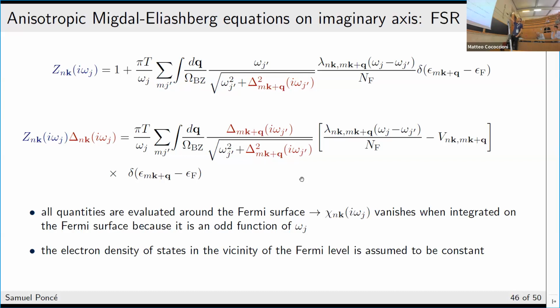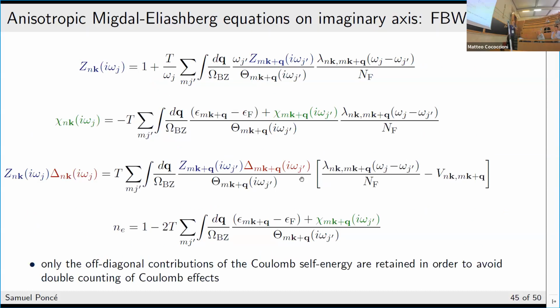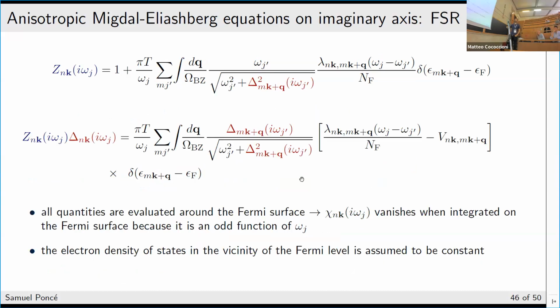Yes, so on the imaginary axis, and this is called this Fermi surface. So what we are doing to simplify is we are assuming that all quantities are evaluated really on the Fermi surface, whereas here there is actually some thickness. So you're accounting for all the things that are happening close to the Fermi surface, but also a bit above and below. So this is more general, and this has been implemented more recently. But traditionally, to simplify this, what you do is that you consider that everything happens exactly on the Fermi surface. And this simplifies the equation because this vanishes when you integrate on the Fermi surface. And so instead, you only have two equations to solve, so it's a bit easier. And so this is called this Fermi surface.